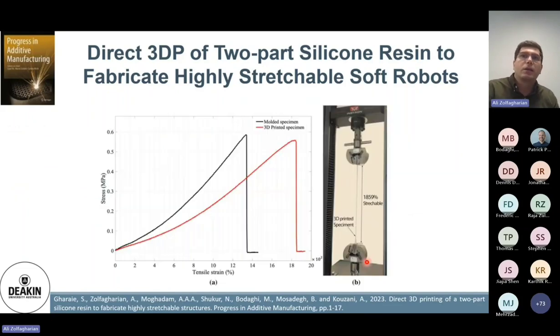The interesting point of this work was that using 3D printing, we could get strain that we could not achieve using molding. The black graph you could see is just using casting of the silicone, and because of the alignment of the silicone in 3D printing, a higher amount of strain could be achieved, that you could see here in this instrument machine, how the elasticity is shown.